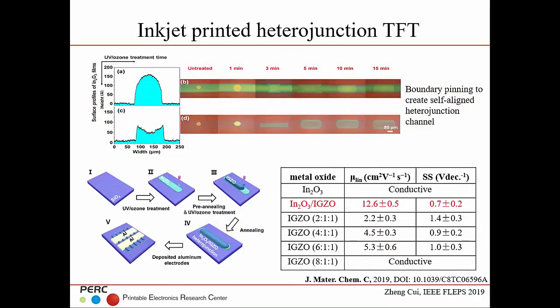We recently also worked on heterojunction TFTs. We know heterojunctions can have very good properties. We also use this self-aligned process. First, we printed indium oxide, then we printed IGZO ink on top of the indium oxide. We define the channel by hydrophobic and hydrophilic regions, so it only overlaps on the indium oxide. In this way, we can build heterojunction transistors with perfectly aligned heterojunctions. And this is the comparison: the heterojunction is much better than the single-component metal oxide. It gave good transistor performance.